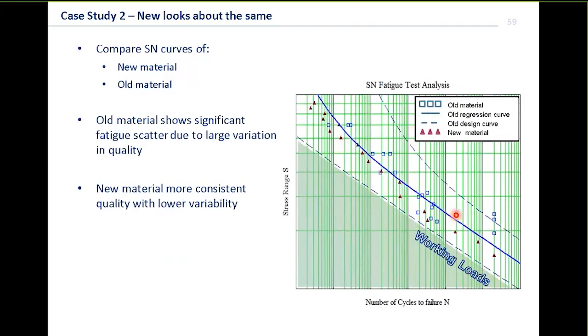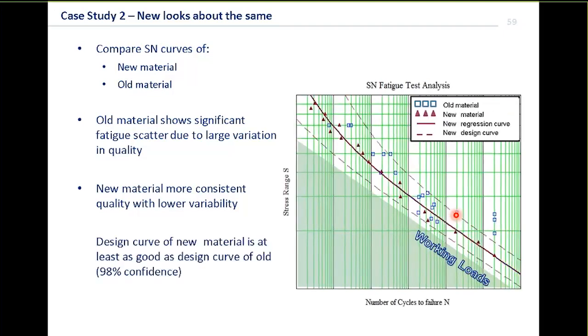Now, if we start to look at that, the old material has a lot of scatter. We notice that its statistical scatter is high. If we look at the new material, even though the regression line is poorer, in terms of how well it fits the curve, we find that its scatter is a lot less. And we find this a lot with new material. As quality processes in the manufacture of materials are improving all the time, what we find is that the scatter is diminishing. And this is what we're seeing in this replacement material.